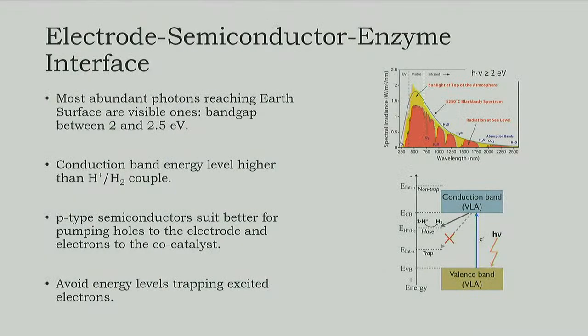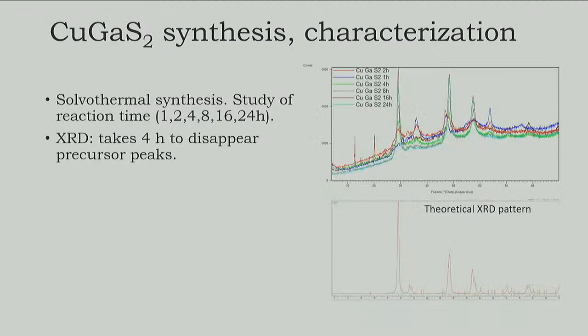So we were working with this for like 1 year and no results at all. And we had to decide, okay, we need a material that is also in this kind of band gap, where the conduction band energy level has to be above, more energetic than the couple between hydrogen and protons if we want to produce hydrogen. And very important, it has to be a p-type semiconductor. Okay? So we found a ternary sulfide here, this copper gallium sulfide, that has all these requirements. So we characterized it by XRD to find how to immobilize it on the surface of the electrode.